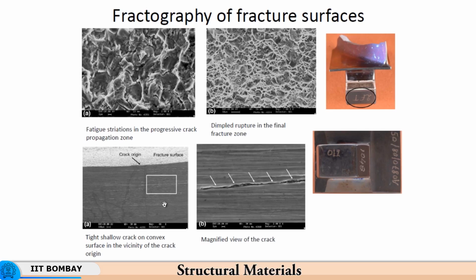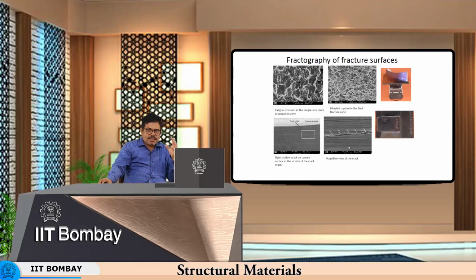very sharp. And if you look further deeper into the structure, you look here. This is a very shallow crack which is visible at very high levels of magnification. So that is what brings us to the initial defect that was present in the material. It was not an external geometric defect, it was a defect which was born internally, and this internal defect then propagated and led to the failure. So this crack propagated during the fatigue.